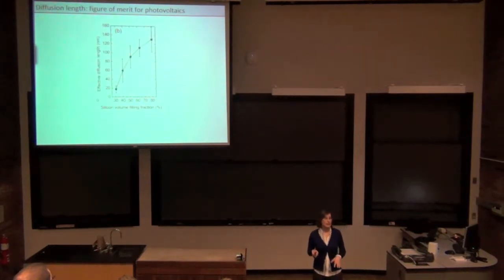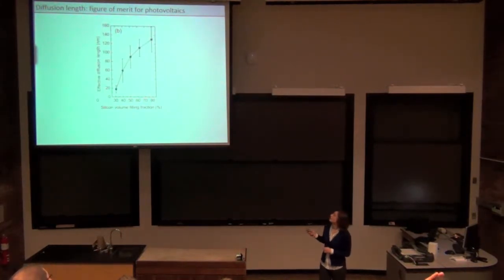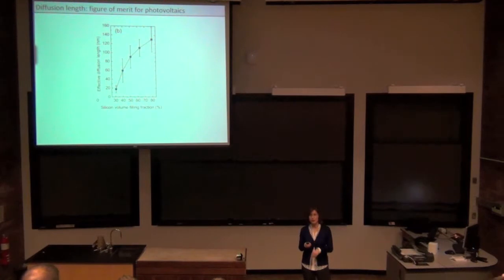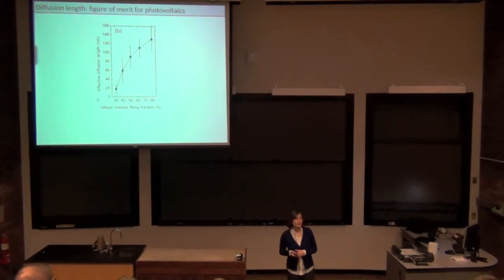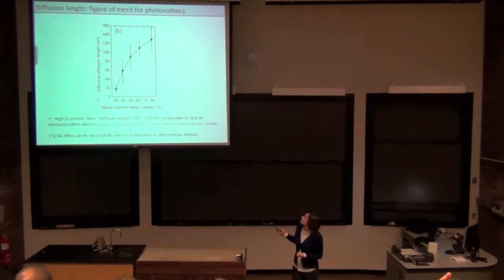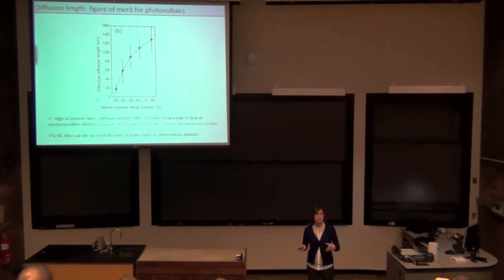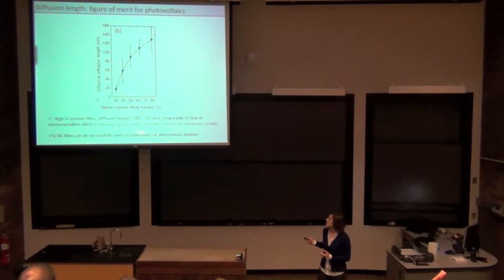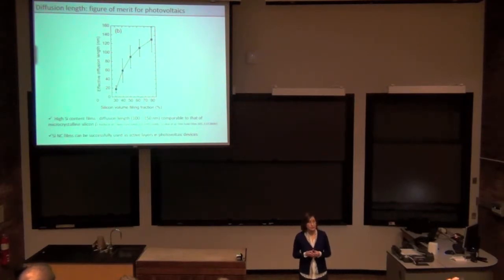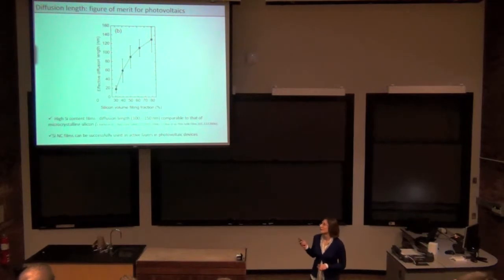And from our experimental data, we were actually able to extract the effective diffusion lengths, which is how far your carrier can potentially go from the spot where it was photoexcited. This is an important figure of merit in photovoltaics, because of course you want to excite your carriers, but you also want to be able to get them out to your electrodes. So what we are finding here is that for the films with composition above about 60%, the effective diffusion length is over 100 nanometers. That is already doable with modern lithographic techniques. That tells us that nanocrystal films can indeed be used as active layers in photovoltaic devices. So that was an important result that came out of it.